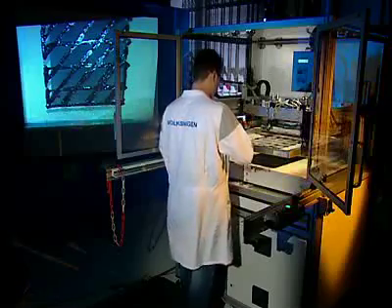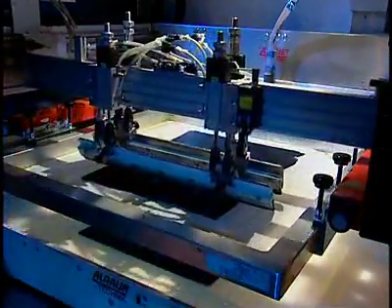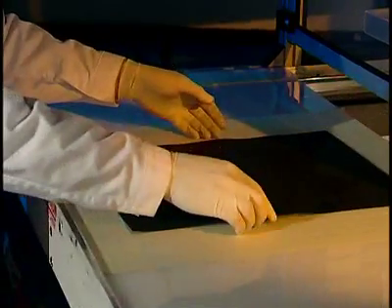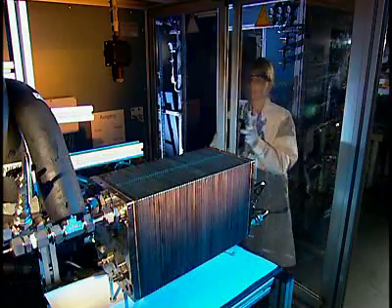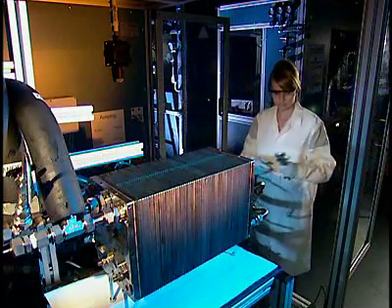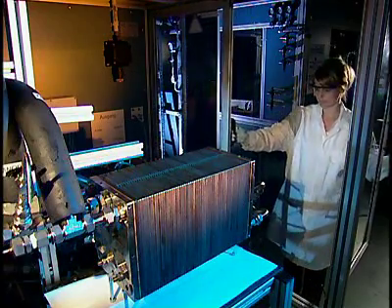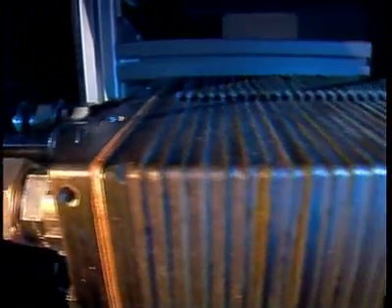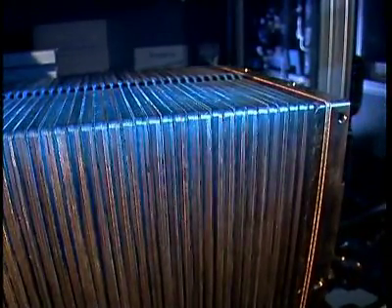In the first step, a screen printing machine coats a carbon tile with a special paste. Then the scientists turn the tile into electrodes and test it on a stack. The results are conclusive. The product water can no longer penetrate the membrane and dilute the phosphoric acid. The cells continue to function at 130 to 160 degrees Celsius, and the higher temperatures provide another benefit. The membrane is less sensitive to impurities in the air.